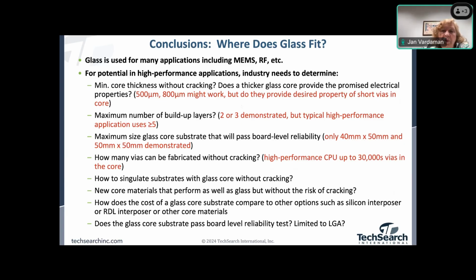What's the maximum number of buildup layers? We've seen 2 or 3 demonstrated, but these high performance applications use 5 or more. We just interviewed people about the co-packaged optics. They think they need 11 buildup layers on each side of a core. We have seen nothing even close to that demonstrated with the glass core.